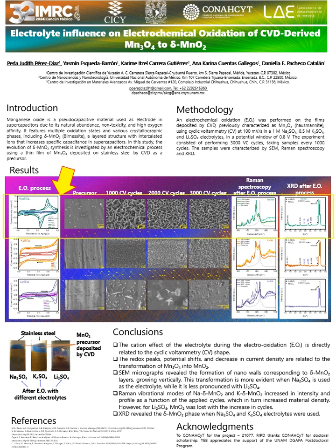Moving on to the results, the electrochemical oxidation with different electrolytes revealed distinct differences between the birnessites obtained. For instance, the CV shape with sodium sulfate electrolyte presents well-defined redox peaks around 0.60 and 0.45 volts. Here are the corresponding micrographs for every 1000 cycles. You can observe how, from a flat morphology, nanowalls appear at 1000 cycles and continue to grow with further cycling.